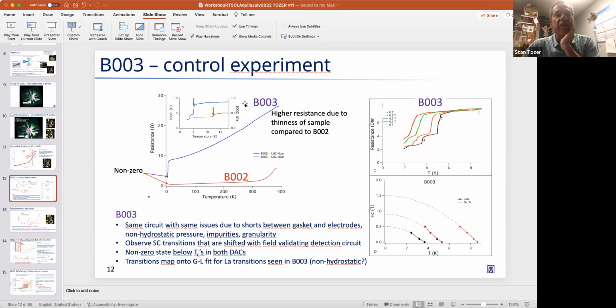As to whether we can see superconductivity with these electrodes, and with the fact that the lanthanum was smeared off to the side, we have this controlled cell, B003, where we can cool it down. We see nothing in the range where one might see any of the lanthanum hydrides, but at very low temperatures where one should see lanthanum and D, we see just that, right? However, it is also non-zero because we're going through some interesting material, or the circuit's not quite right.